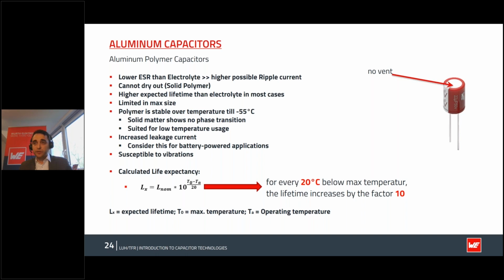It is a solid internal structure, the polymer, and is somewhat susceptible to vibrations as it could break rather than just shake up a liquid. You see the lifetime calculation here is similar, but a little bit different. So here it goes: for every 20 degrees you stay below the temperature, you will increase the lifetime by a factor of 10. So for the electrolyte, it's 2 to the power of 20 over 10, so times 4. And here it's times 10.